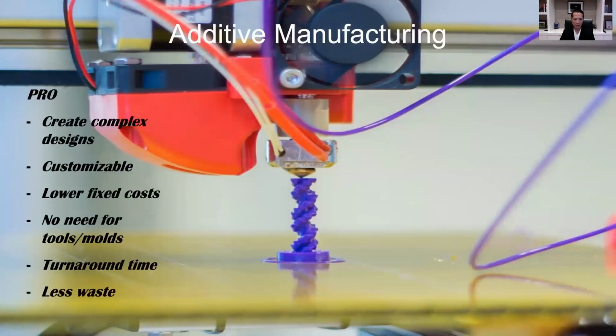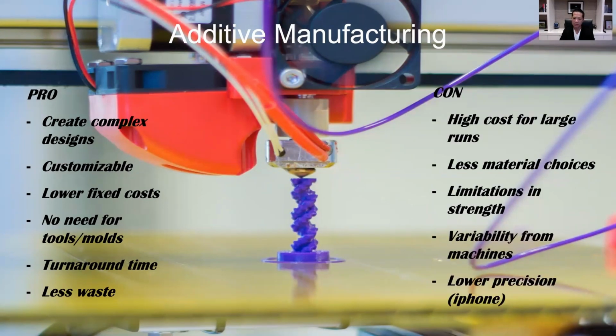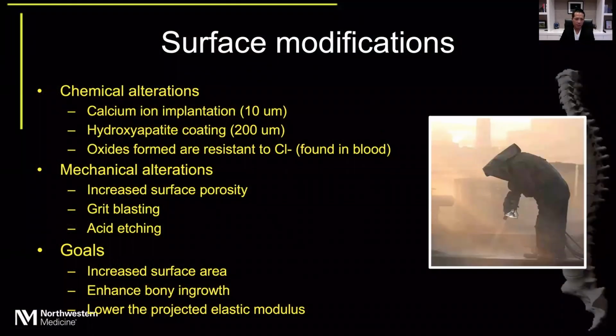Additive manufacturing creates a number of advantages in order to create structural cages that Dr. Anderson will be talking about in terms of being able to create complex designs. But there are some limitations with the material that we use in strength, and there's some variability from the machines that are created. Surface modifications have led to increased osseointegration, which include both calcium ion implantation, hydroxyapatite coating, and there are mechanical alterations that have been described, including grit blasting and acid etching. All of these applications have goals in mind, including increasing the surface area, enhancing bony growth, and lowering the projected elastic modulus so that the surface itself can lead to hopefully less subsidence.